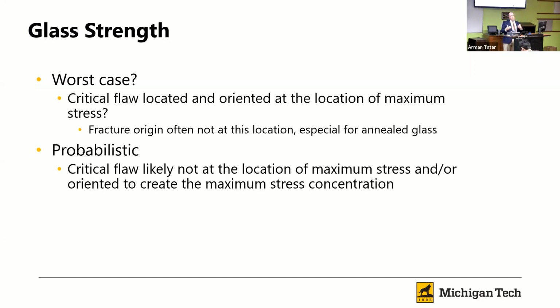But what we find, especially with windows, and especially for annealed glass, is that when we break glass under load, it doesn't always fail where we expect. In fact, the fracture origin often does not occur at the same spot our maximum principal stress was at. And so that kind of causes us some concern because we may actually be failing at a lower stress than what our maximum principal stress was. And furthermore, it was at a location other than the maximum principal stress. So that kind of makes it a little more difficult.